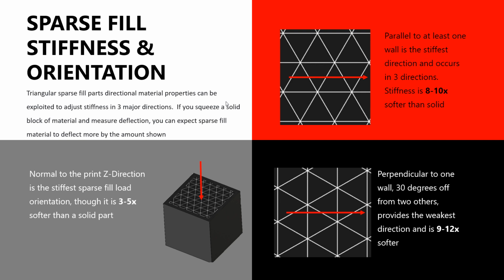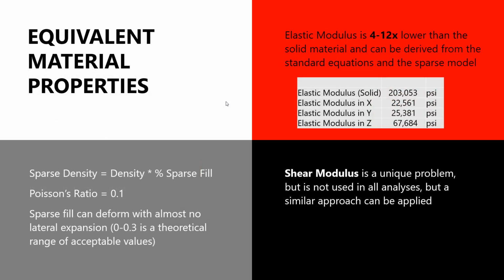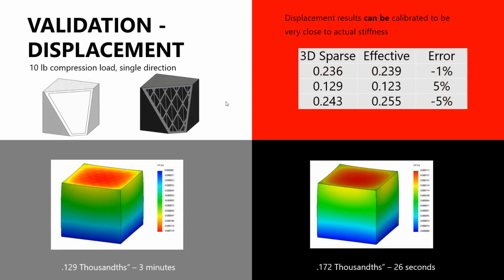And then directionality-wise, with 30-degree increments, you're seeing a pretty big range of differences depending on the orientation relative to the triangles. All that to say, it's complicated, right? So what I did is I created some equivalent elastic modulus parameters, calculated some equivalent Poisson's ratios and densities, and then ran it and tried to validate it, and I can calibrate these results pretty close, but they're never just consistent.